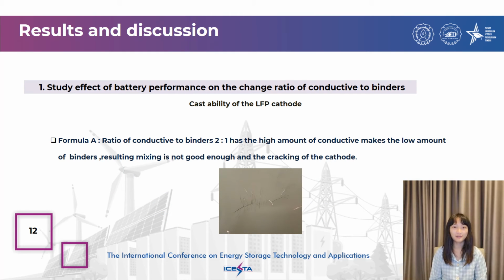As the previous slides show, when a higher ratio of conductive is used with a low ratio of binder, adhesion is compromised. As is known, the binder helps to disperse and improve adhesion of the slurry to the aluminum sheets. When the binder ratio is too low, the resulting slurry will have issues with adhesion and cracking of the cathode. Therefore, my findings show that you should not use a conductive to binder ratio 2 times higher than that of the binder.